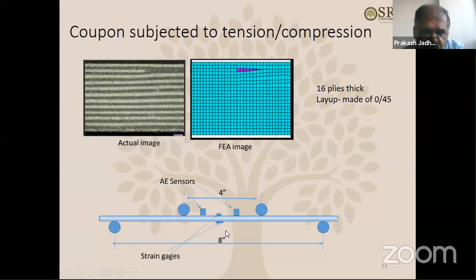So we made the coupons, and first we tested the coupon with the ply drop near the compression surface. In the second case, we placed the coupon where the ply drop is near tension, and then we tested them to see how they behave. And of course, there are strain gauges and this AE sensor. AE sensors are acoustic emission sensors.